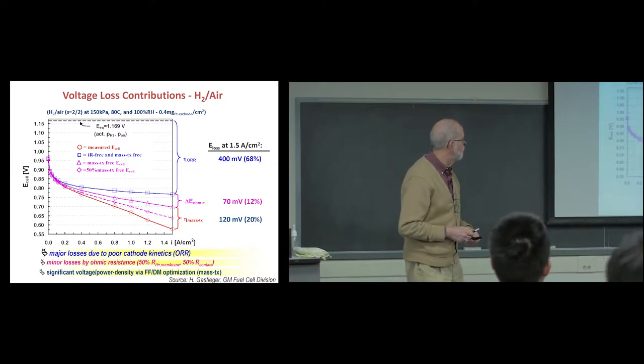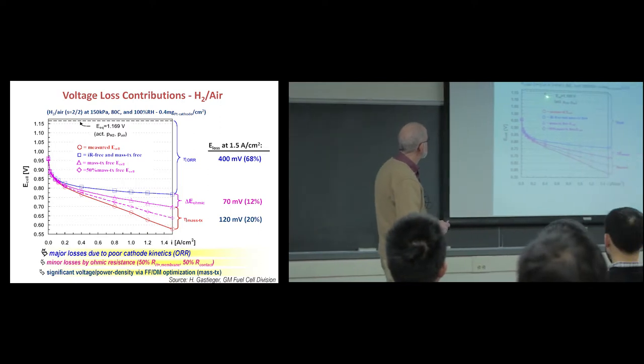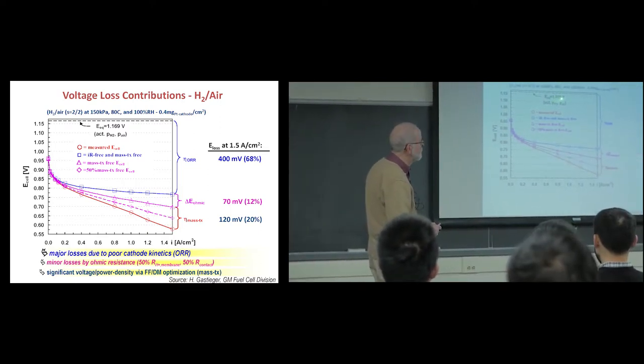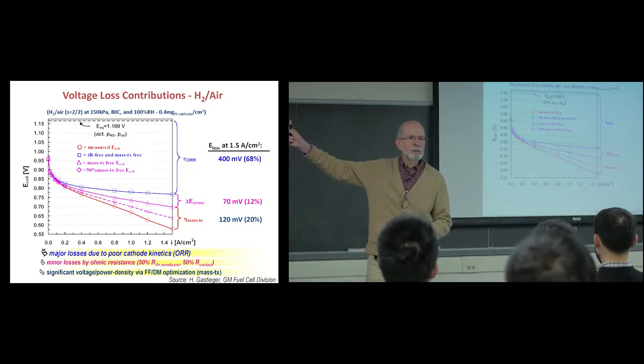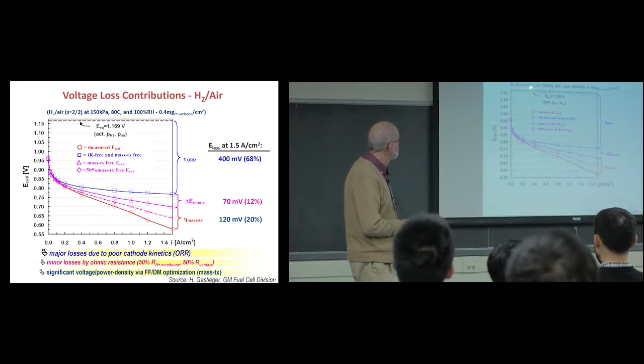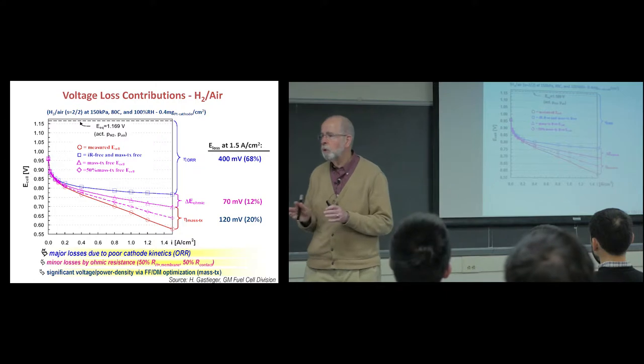Okay. So let's look at this. It says that the equilibrium potential is 1.169. It's not 1.23, as we put over here, and the reason is this is not under standard conditions. It's running at 80 C, not at 25 C. It's running at pressures above the pressure that we had before, and it has a certain amount of catalyst in there. So it turns out that the equilibrium potential for that cell is a little below 1.23, but it's so little below it, you wouldn't notice in most applications.